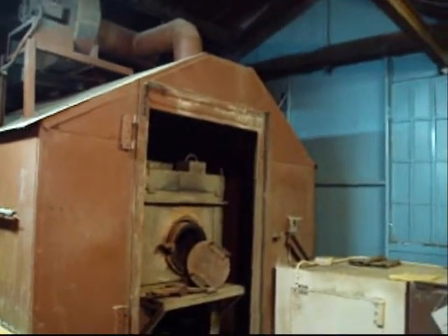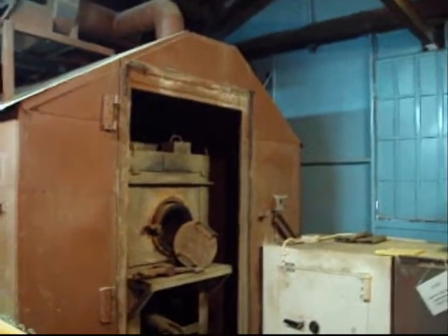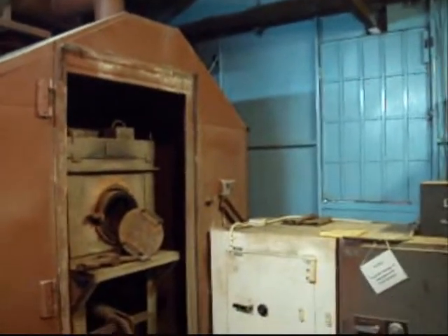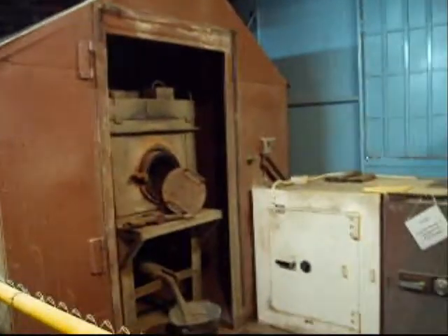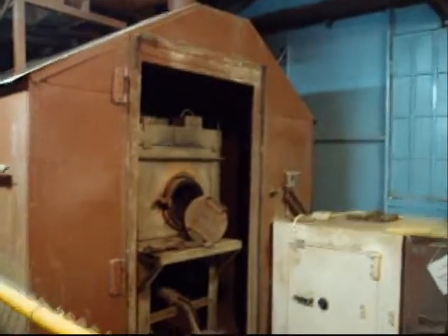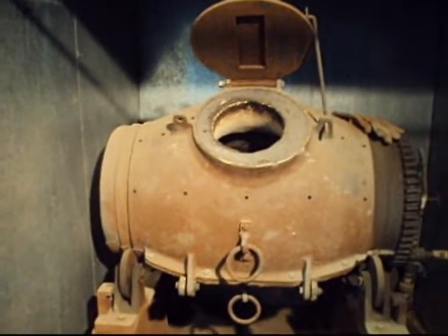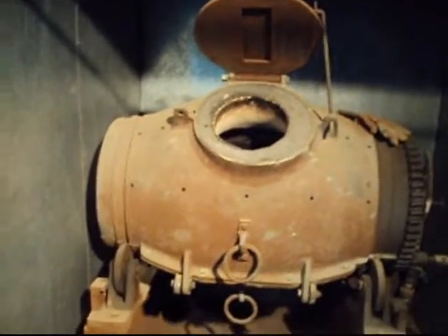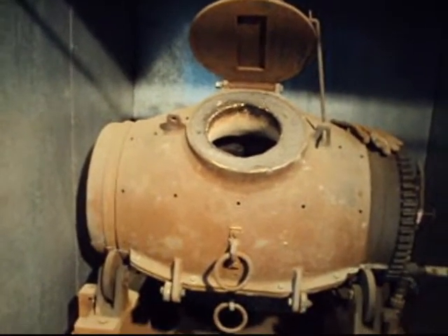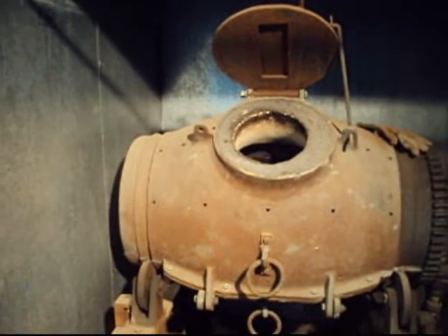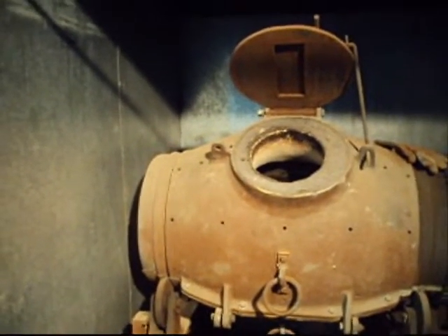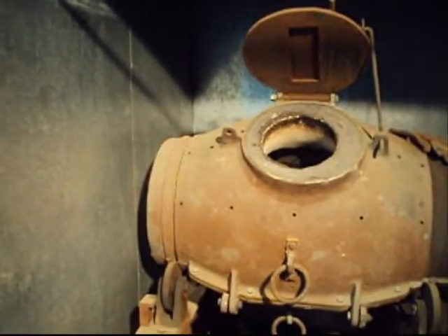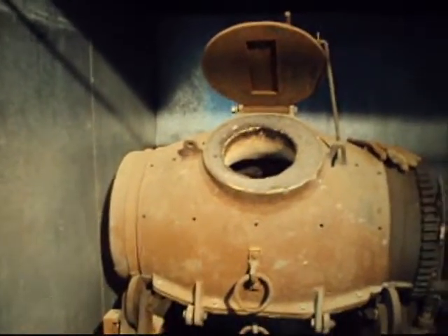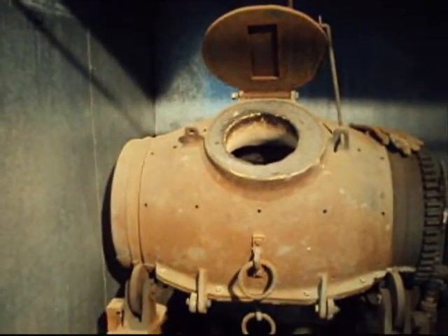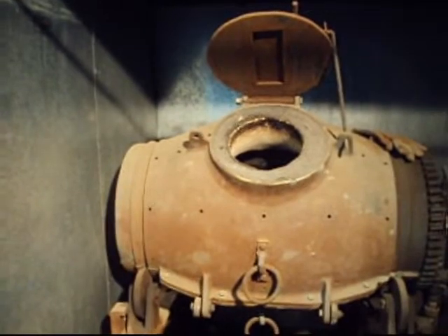This was as far as the company processed their gold here, but you will see they installed in the very last year a bullion maker that would process it further. Here is the bullion furnace where all the material was melted and it would separate according to weight, with the heaviest on the bottom. And the first thing out of it would be the slag rock, and then the next would be the lighter metals, but very last would be the gold at the very bottom, almost in bullion state, 99% pure, poured in the cast iron bullion bar containers, as you can see down there.